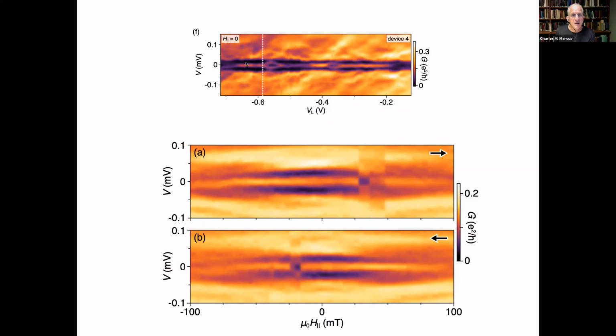If I sit here at a place where it's kind of about to split and I sweep the external magnetic field, I apply a field, you see that at the coercive field, the place where the field reverses and goes through zero, also the zero bias peak splits. So this is a place where the external magnetic field was just on the edge of being large enough to push this state to zero. And when you go through zero external field, it splits. When you sweep this way at the coercive field, it splits again when you're going back in the other direction.